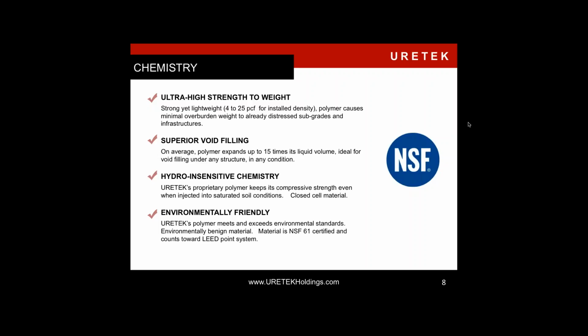Again, that's free rise under confinement, not quite as much as 15 times, but that's good for void filling and stabilizing structures. The material we use is also hydro-insensitive. That's our buzzword for saying hydrophobic. So the material can be injected into water-laden soils or even standing water. The water will not affect the structure of the material. It will still set up and perform.